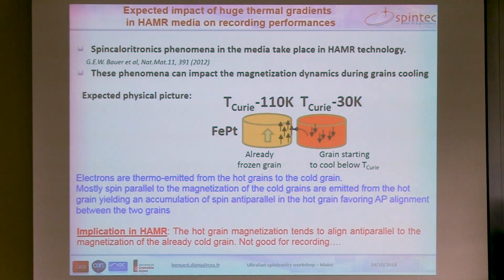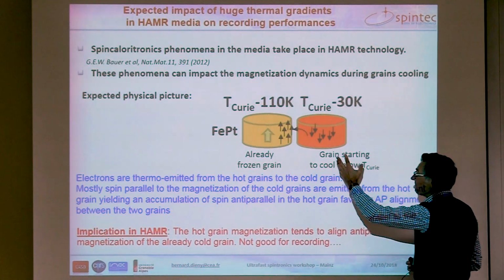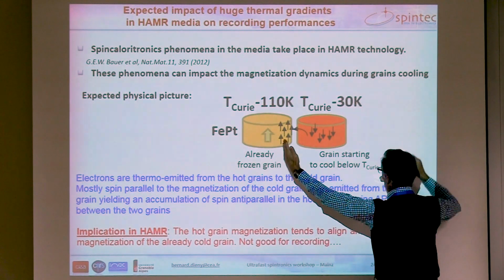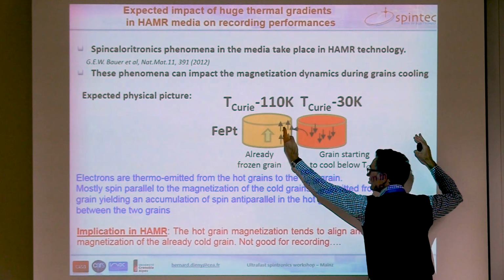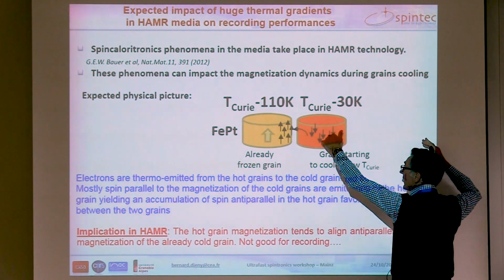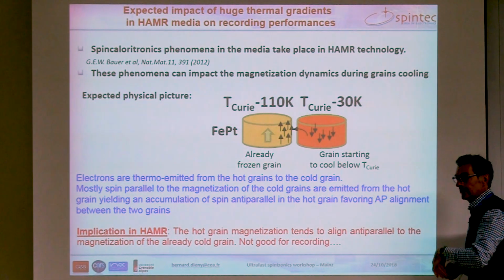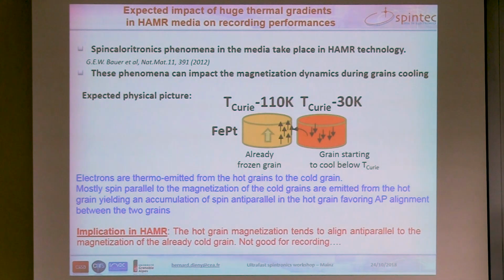This is basically what we expect, that during the cooling, the hot grain will tend to align anti-parallel to the already cooled grains. And of course, this is not good in terms of recording, because it means that if we want to write a 0 here, if this grain is already up, this one may orient in the wrong direction. So I'm going to show that indeed this is something which may happen and has to be taken care of.